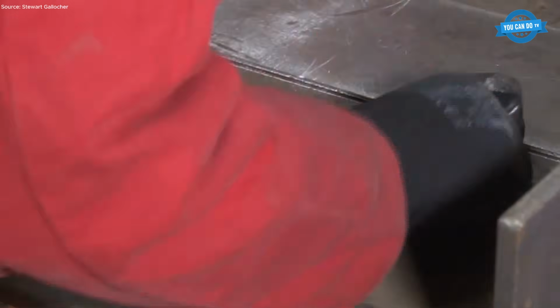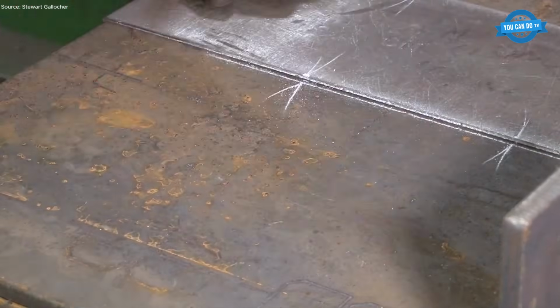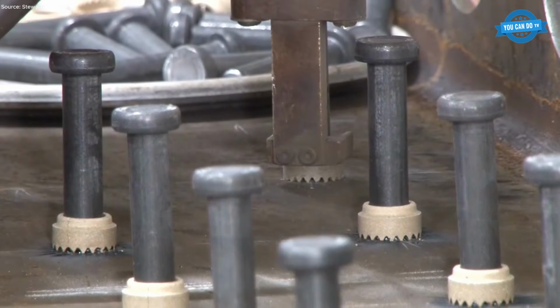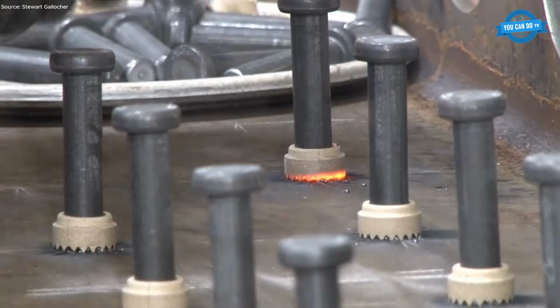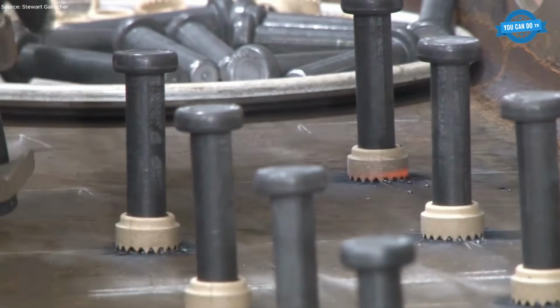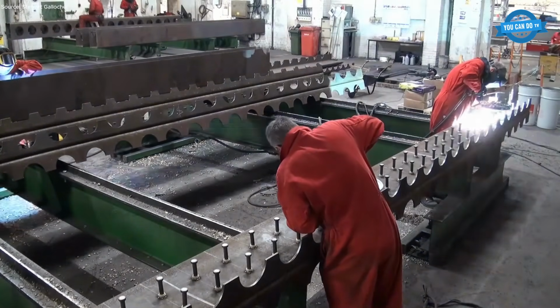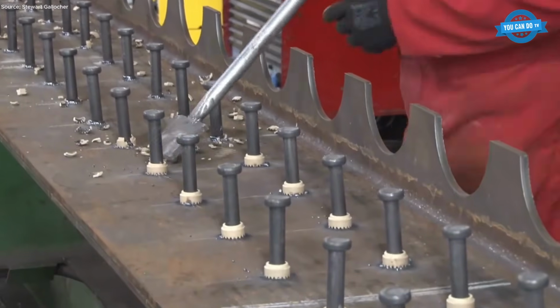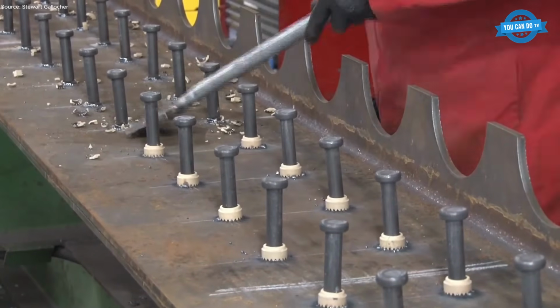Assembly takes place on rigid fabrication beds designed to control distortion. Components are aligned using calibrated fixtures before multipass welding begins. Heat input is monitored to manage shrinkage and residual stress, particularly critical for heavy box sections and complex node connections. Where required, automated welding systems deliver consistent bead geometry and repeatable deposition rates across long seams.